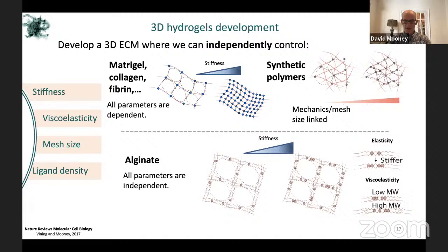And so with an alginate gel, if one cross-links it to a low level to make a relatively soft gel, as indicated by these few red dots, basically bridging adjacent polymer strands where we have these G block structures, actually all the polymer chains end up falling into a specific alignment. And then as we add more and more cross-links, we in essence just occupy more and more of these locations that are already aligned adjacent to each other. So we can make the material more stiff without changing the nanoscale architecture. So we don't change the mesh size or diffusional transport.